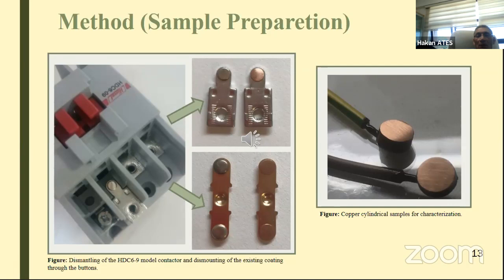From the figure on the left, you can see the dismantling of the HDC6-9 model contactor and the dismounting of the existing coating from the buttons. These coatings are removed with sandpaper. From the figure on the right, you see a cylindrical copper sample. This sample is cut and dismounted for characterization.